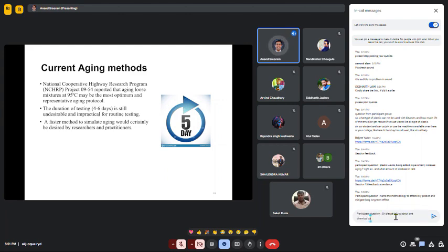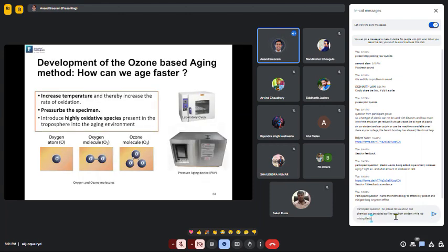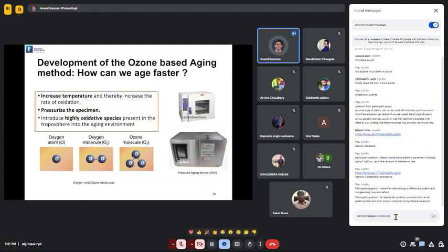However, the 4 to 6 days is still kind of undesirable and impractical for routine testing. So we did some work on how we can reduce that 4 to 6 days to even less than that, using just one day. The way we did that is we developed what we call the ozone-based aging method.